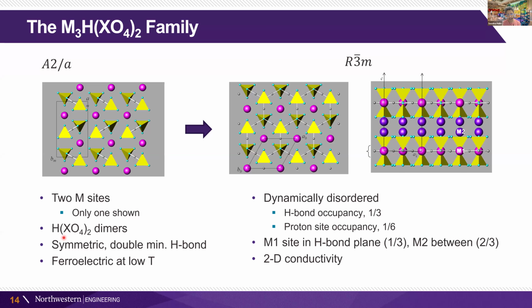And at the high temperature, that hydrogen bond gets distributed over 3 different sites. And it's a double minimum hydrogen bond. So the occupancy then of the protons in those sites becomes 1/6. And there's very high conductivity in the plane because of that structural reorientation that happens in the plane. And it's a little bit more of a 2-dimensional conductor than a 3D conductor.